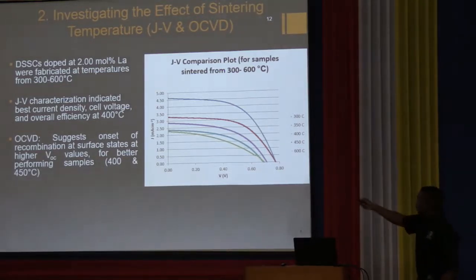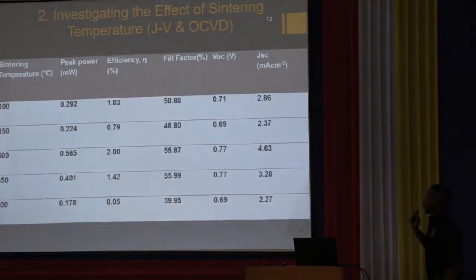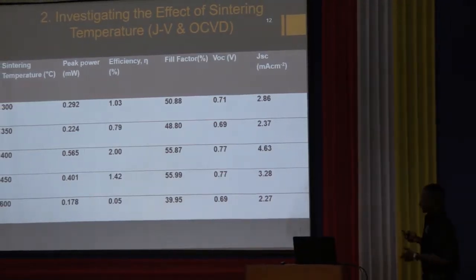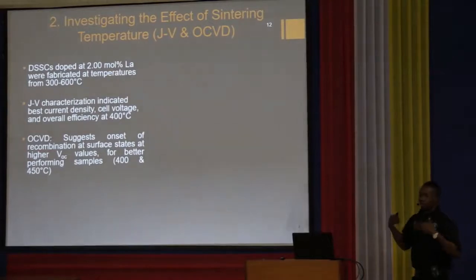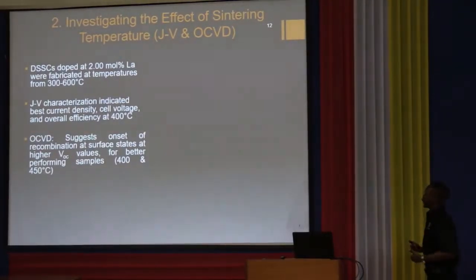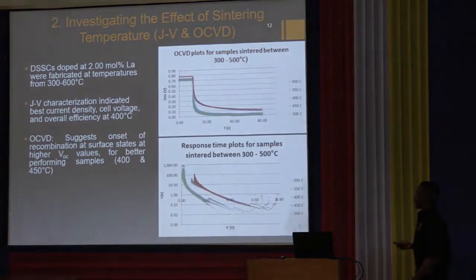And again, you can notice that this particular sample in blue is pushed up to the upper right, has a higher intercept here, a larger intercept right here, and this corresponds to a sample that was sintered at 400 degrees Celsius. Compared to the other samples, the 400 degrees Celsius sample had a higher efficiency, higher cell voltage, and higher cell current. This essentially told us that the best sintering temperature to use was 400 degrees Celsius.